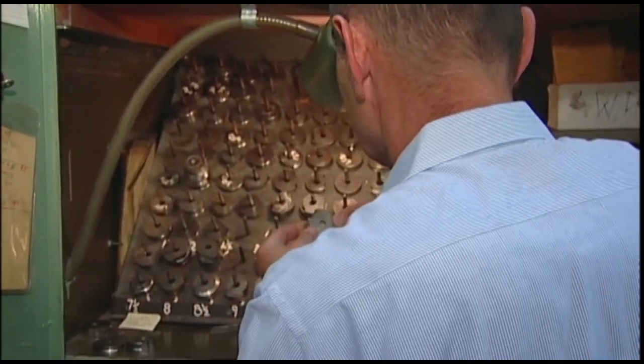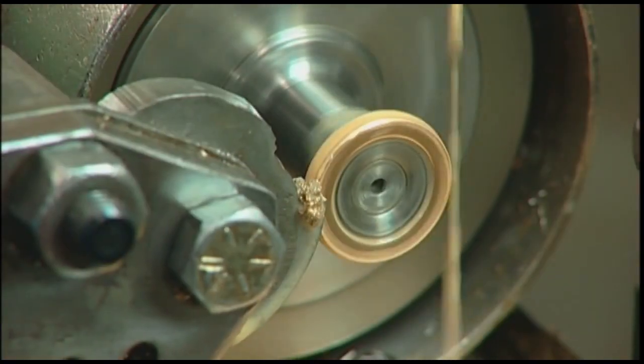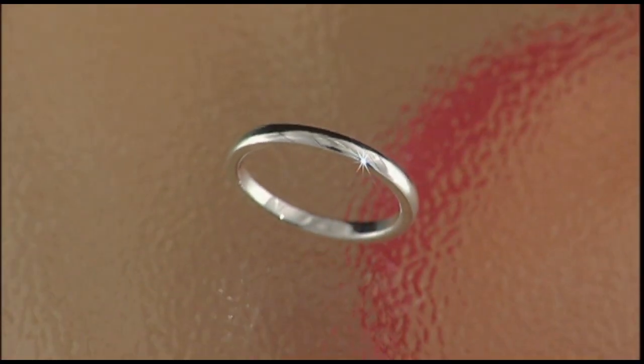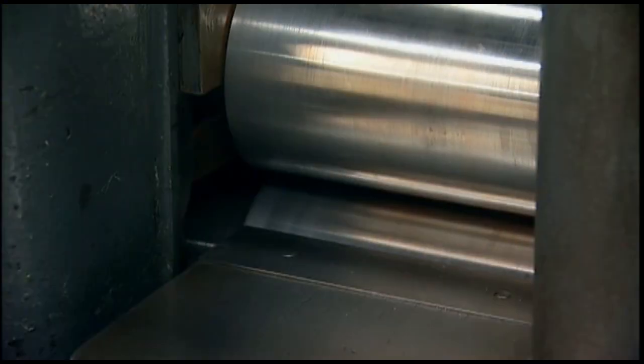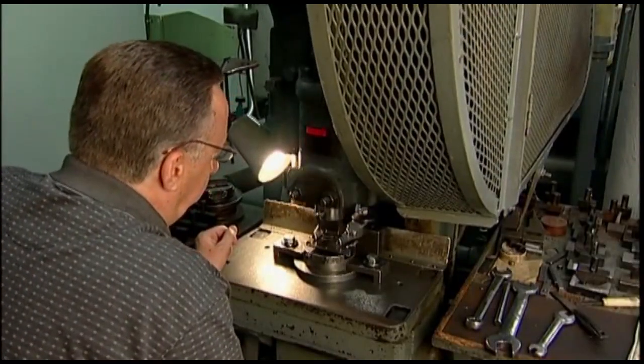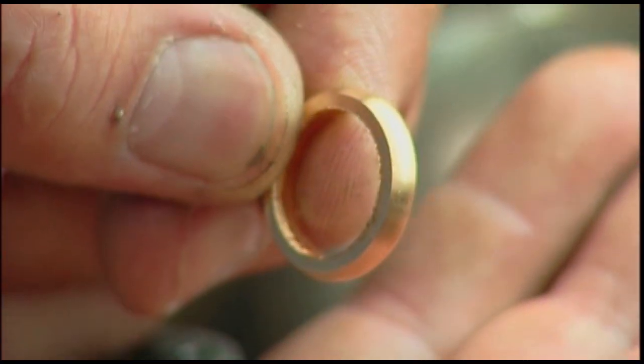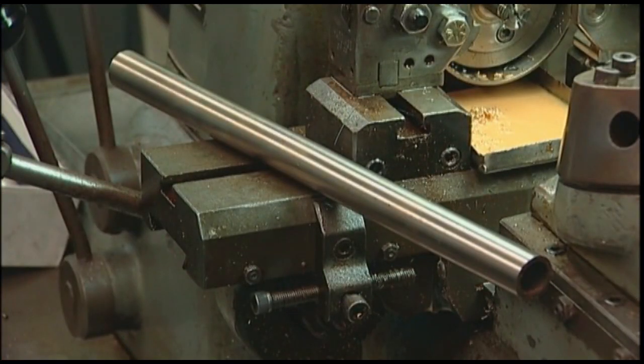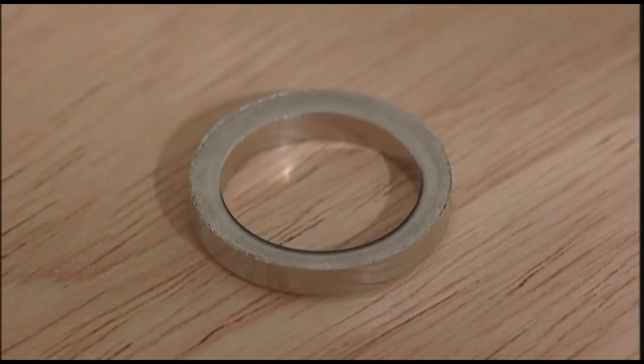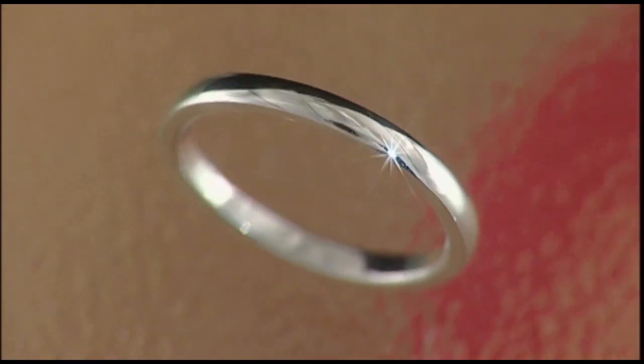Jabel uses many variations of die striking as well as other manufacturing methods in the production of our pieces. Our seamless wedding bands are formed using two different processes. One involves a basic blanking operation. Metal is rolled to the desired thickness. Washer-looking blanks are struck and then turned inside out and cut on a lathe. The other way is to cut extruded tubing to the desired shape. The seamless metal allows us to shrink and stretch the pieces to obtain the proper finger size.